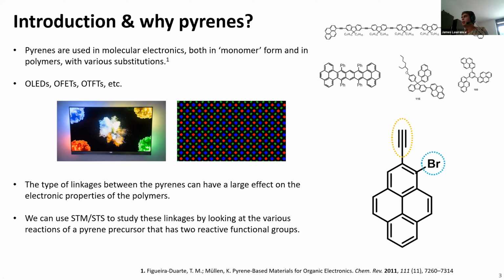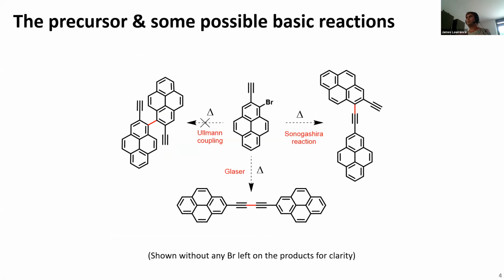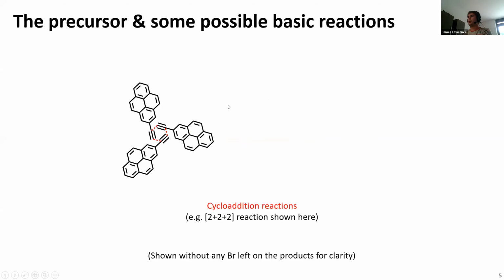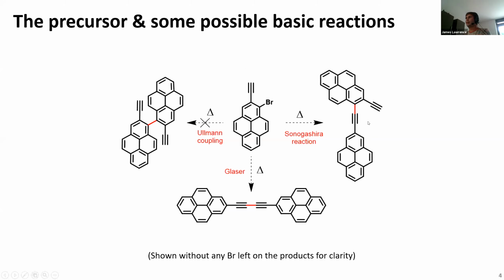So what we're going to do here is use on-surface chemistry to study this precursor with the alkyne and the bromine substituents, which can both undergo various reactions on the surface and form lots of different linkages. If we look at the basic reactions the molecule can undergo on surfaces, there are a few basic ones, such as Ullmann coupling, which in this case, if you think about it on a surface, is probably not going to happen because there's quite a bad steric clash at the sides here. But it can also undergo alkyne-alkyne homocoupling, for example the Glaser coupling, or heterocoupling between the bromine position and the alkyne, forming a bond like this.